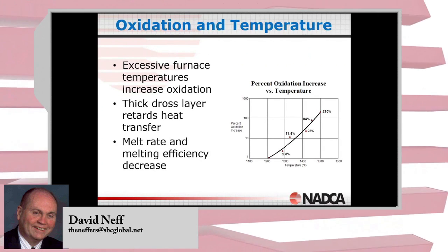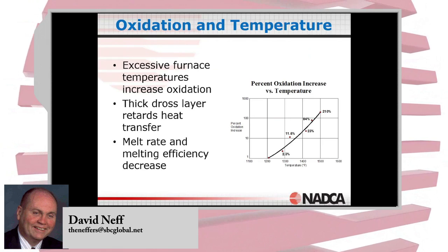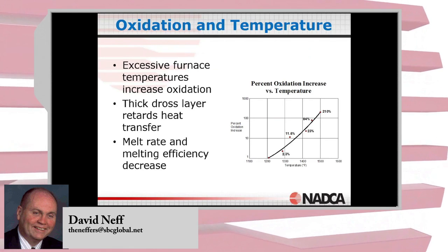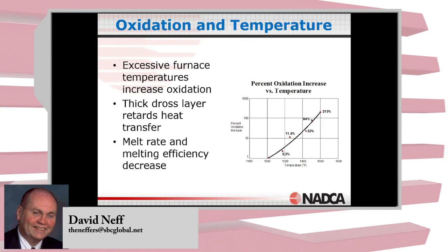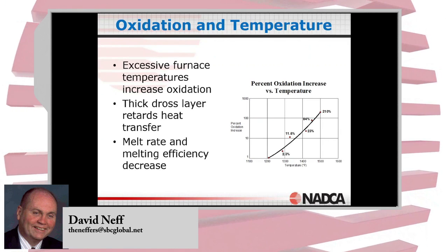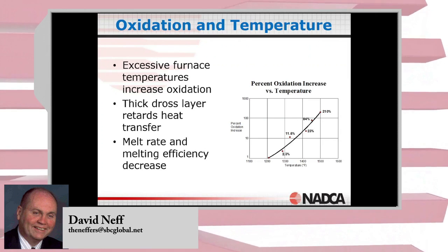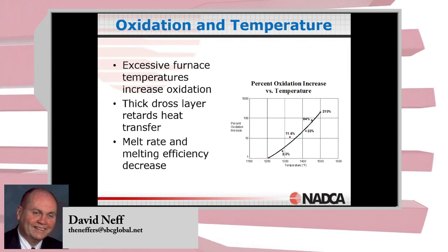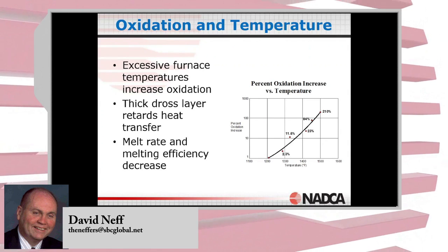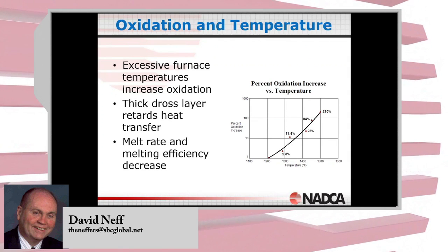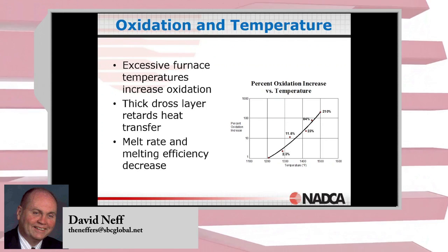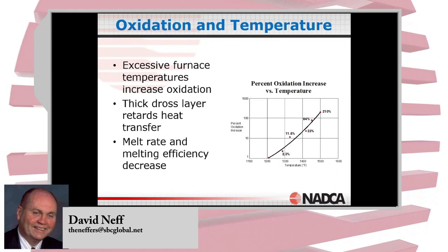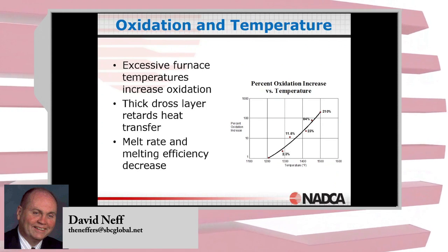Now, oxidation increases exponentially with temperature, as you see in this chart, and therefore it's imperative to maintain as low a temperature as is practical in the melting operation, and clearly again to make sure that one is utilizing temperature measurement capability that is accurate.